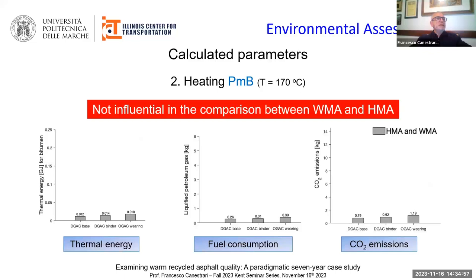The calculated parameters for the heating of polymer-modified binders demonstrated that this phase is not influential in the comparison between warm and hot recycled mixtures, because the heating temperature is the same in both cases and equal to 170 degrees C.